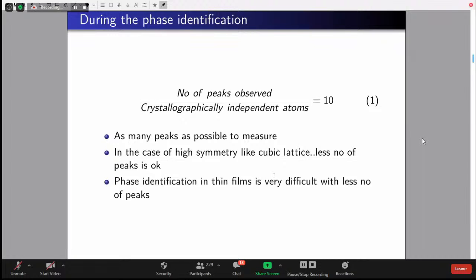This trouble comes when we see thin films. For the phase identification of thin films, the thickness is usually a few nanometers, at most half a micron, which means 500 nanometers. Then the crystallite size will be very small, and usually they will be oriented in one preferred direction. So in that case, we will see only one peak, in rare cases a second peak. In those cases, we should find another way to figure out what kind of phase it is, like TEM analysis and other things. But when it comes to powders, we should measure as many peaks as possible.